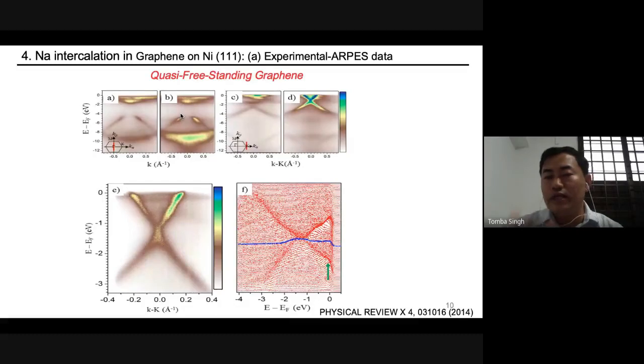Now the interesting point is the band structure taken at the K point. The first one, C, is from before intercalation. We don't see a proper Dirac cone, but pi states are available here around 2.7 eV below the Fermi level. But here, after intercalation, we observe a nice Dirac cone just below the Fermi level.